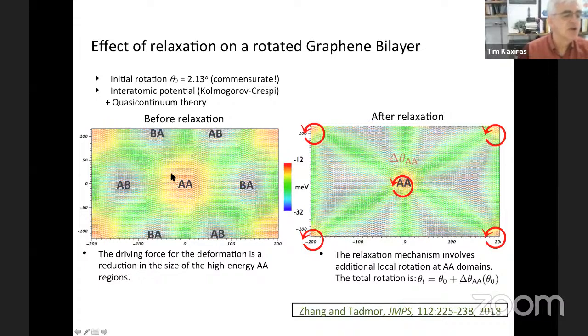So this is before relaxation. You see this AA stacking, and as I described earlier, BA and AB stacking, and the boundaries between them, these are also called domain walls. And this is what happens after relaxation. The AB and BA regions expand significantly because those are the low energy structures. The AA regions contract very significantly. They shrink to very small regions. And there's an additional twist of the AA regions beyond the twist imposed on the entire bilayer system. So the local rotation is the original relative twist of the two layers, plus an additional twist at the AA regions.